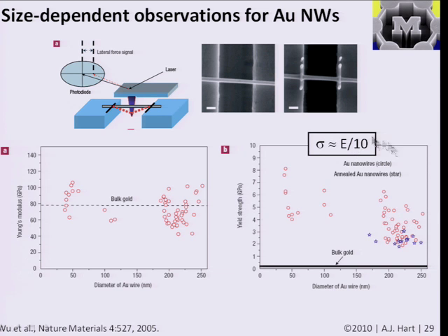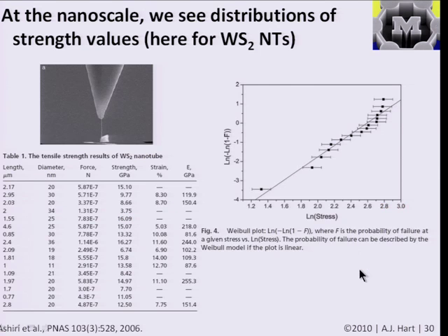The other interesting thing to me here is that we see the material approaching this limit that I proposed, of strength being about the Young's modulus divided by 10. So here we can say that this wire is yielding by actually deforming the bonds until they fail, and our strength is not limited by other aspects of organization of the material. It's certainly a big difference between this scale and the macroscale.